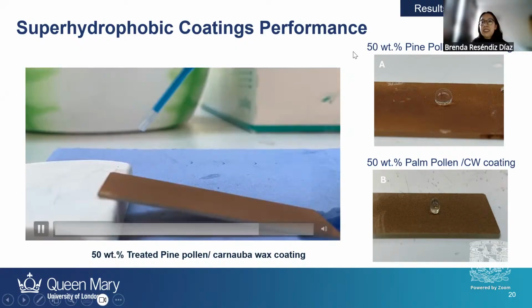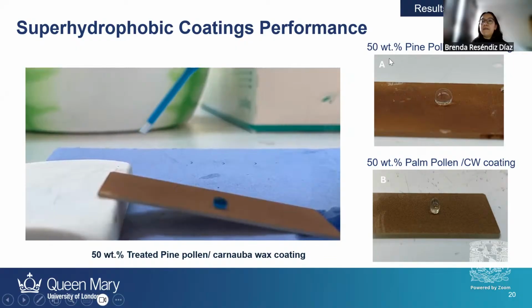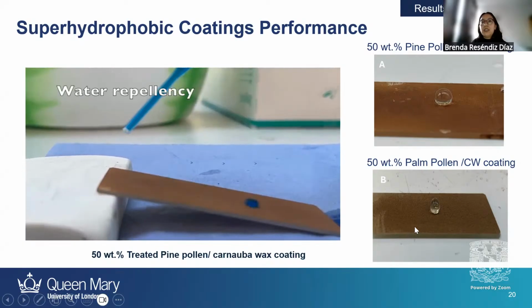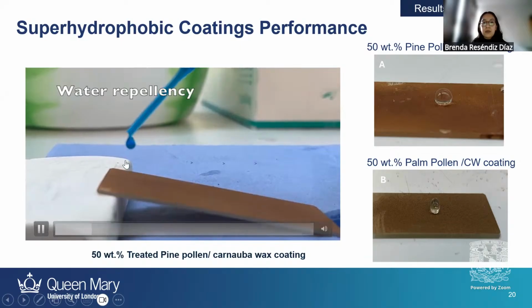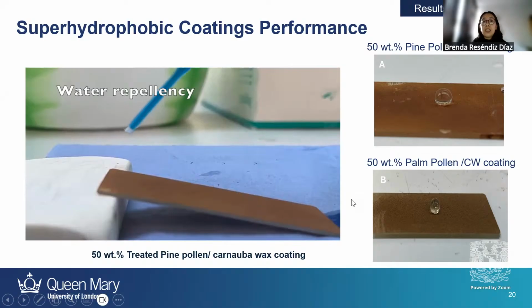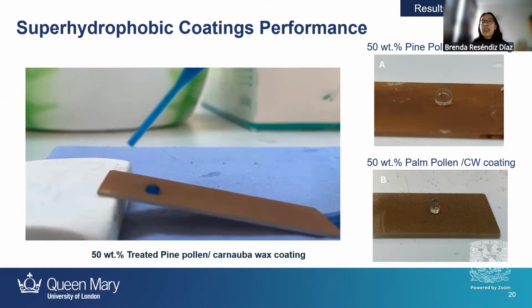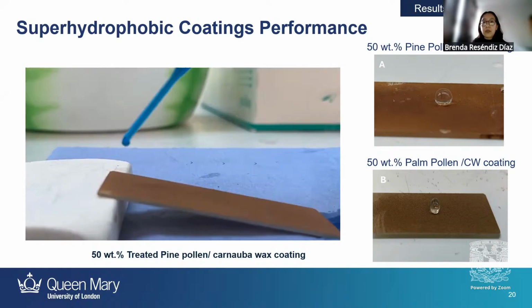Here we can see a 50 weight percentage pine pollen Carnauba wax coating, which was one of the ones with higher water contact angles. Here's what I was saying about the rolling: you can observe that the droplets roll very easily through the surface. So they have this self-cleaning action and also anti-fouling properties.